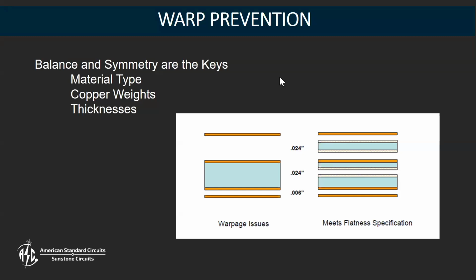So really, that's one of the things that we like to encourage is keeping everything as balanced as possible. Obviously, sometimes there'll be need for some imbalance or some unsymmetry, but balance in the material types that you're using. If you're using mixed packages, the copper weights, trying to keep the 2 ounce symmetrical with the 1/2 ounce or the 1 ounce on those internal layers, and then also the laminate thicknesses as well as the pre-preg thicknesses. So balance and symmetry.